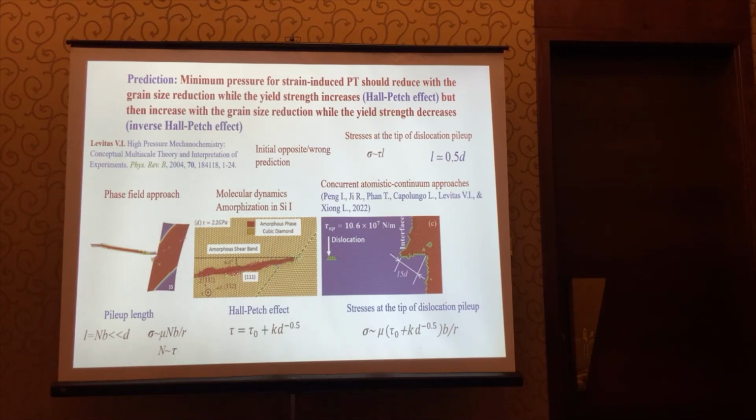Where is the problem? With all our simulations with three different methods, we found that at large shear stresses, dislocation pileup mostly localizes at an obstacle, at a grain boundary, producing superdislocations. And it's much smaller than grain size, so this is not a limitation. But then we need to apply the equation for a superdislocation, in which the stress concentrator is proportional to the number of dislocations.